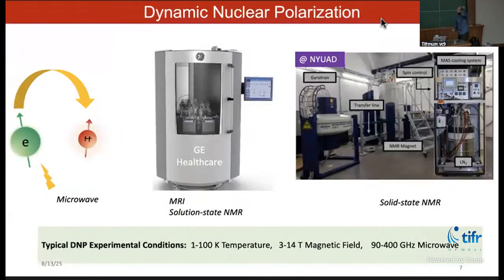So depending on application, if someone wants to do DNP for MRI application or solution state NMR application, this is how the setup looks like. If someone wants to measure DNP for solid state sample, this is how the DNP setup looks like. It's basically NMR with a few add-ons. And the add-ons can be predicted from the experimental conditions for DNP. Most conventional NMR experiments are done at room temperature, but DNP happens efficiently at lower temperature. The temperature range is typically from 1 to 100 Kelvin for DNP.